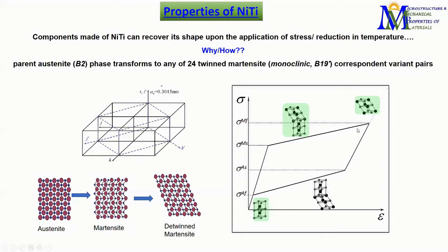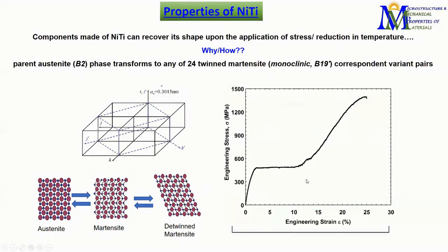Starting from here, we have a completely, fully martensite structure. So this is basically the martensite finish stress. If we unload from here, it comes back to austenite. Once again, a complete reversible phase transformation occurs and it reaches austenite. So this entire amount of strain that is generated can be recovered, and this strain is called the recoverable strain. Recoverable strain consists of not only the elastic strain, but also the pseudo-elastic strain. This process is very similar to elasticity in terms of strain recoverability, so it is called pseudo-elasticity. So you can see this as a stress strain diagram. This is an experimental one.